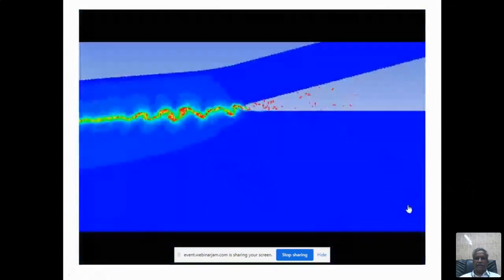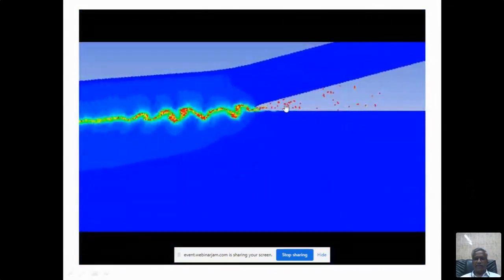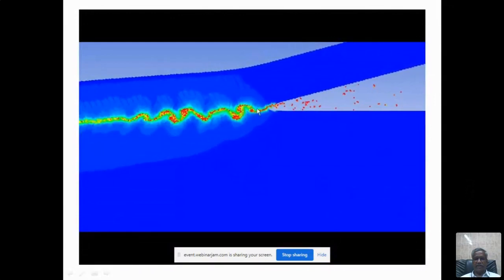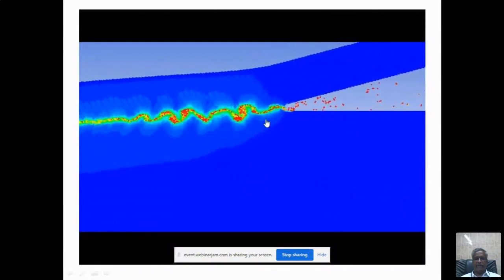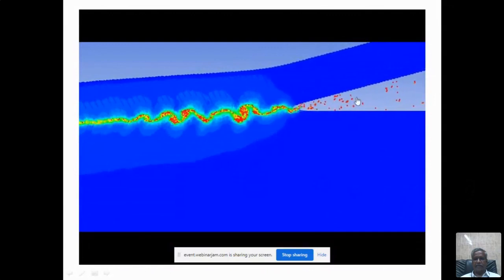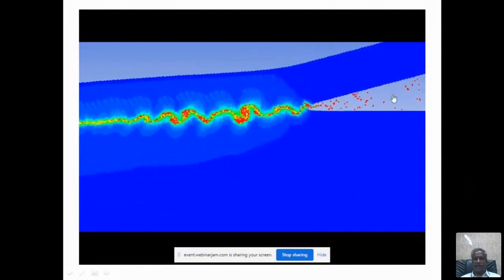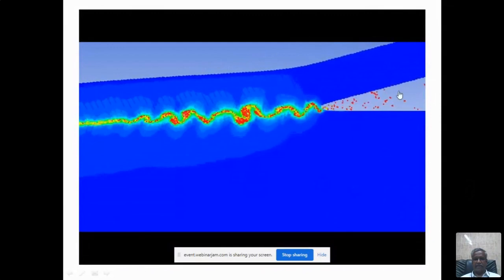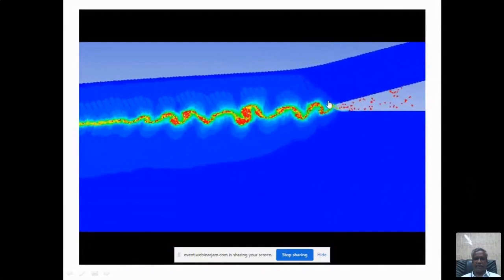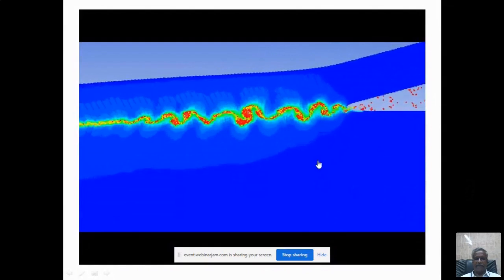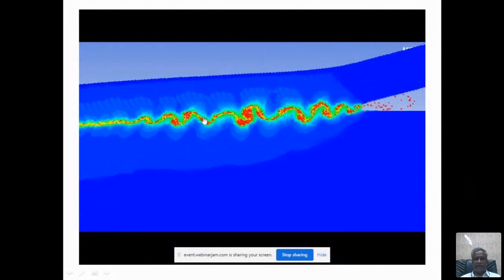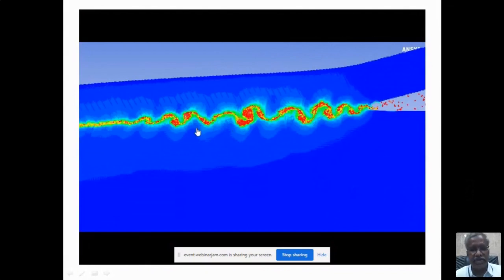Yeah. So another animation, you can see how the surface layers are removed. Because of the collision of the interface, as I told you, a lot of energy is produced, and these vector particles which are coming out are all the oxide particles removed from the top surface of the flyer plate and the bottom base plate. So at the collision point, you will get this type of a jet. In explosive welding, it is called the wavy interface. This interface is a typical characteristic feature of an explosive welding or explosive bonding component.